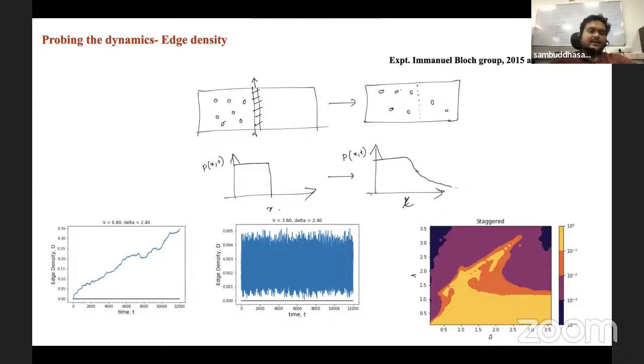And it turns out that, for example, if you look at the bottom left plot, you will see that it grows with time. So that's a sign of not being localized; it can be critical or ballistic. Or if you see the bottom middle plot, you will see that the numbers are very tiny and it is fluctuating. So it's a sign that the gas is not spreading at all.